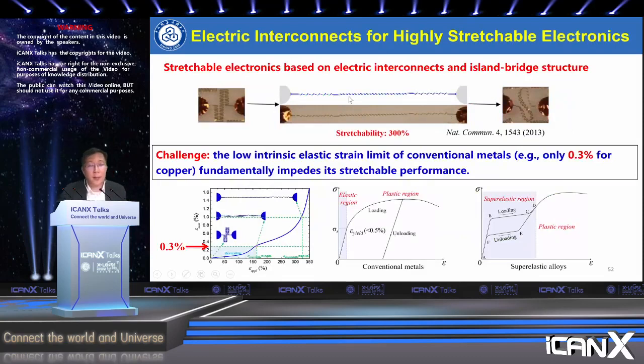And there's another very important interface we need to take care of, which is the electrode. Commonly they use stretchable electrodes. Stretchable electronics use electrical interconnects and island-bridge structures. It achieved very high stretchability, but due to the low intrinsic elastic strain limit of conventional metals, such as about 0.3% for copper, when it recovers, it usually doesn't go back to the original state. This will impede its stretchable performance.